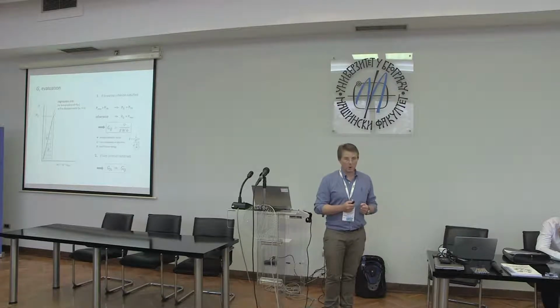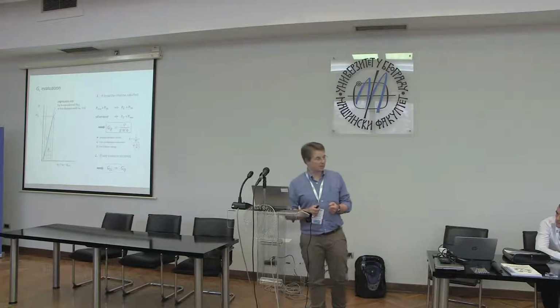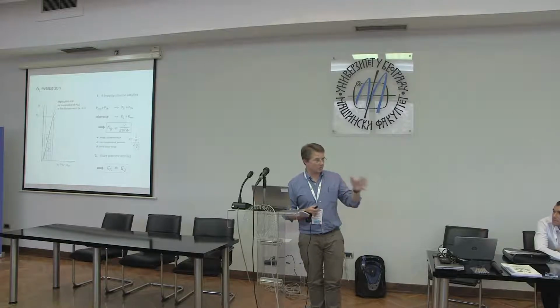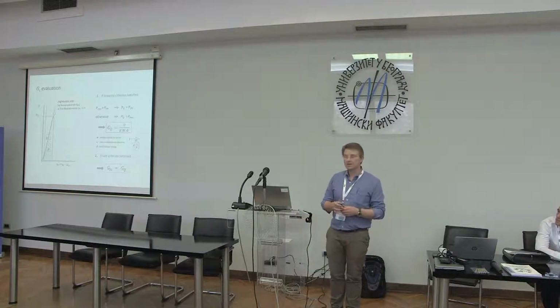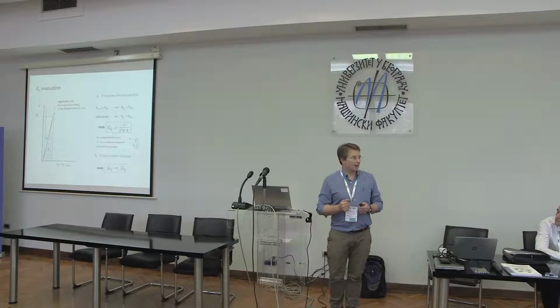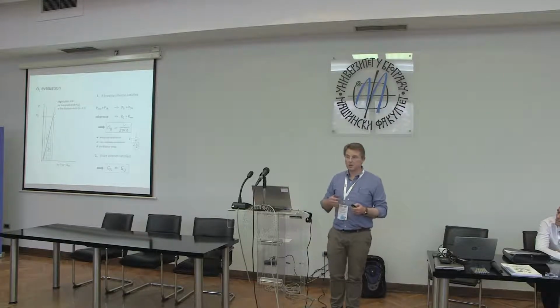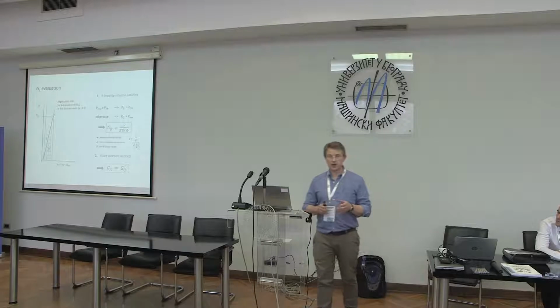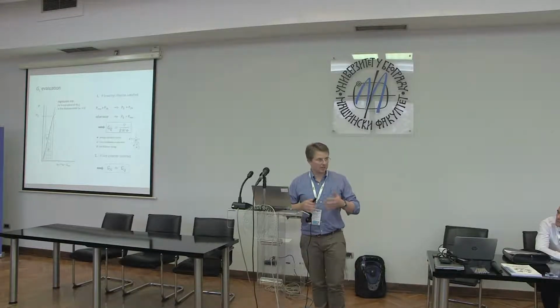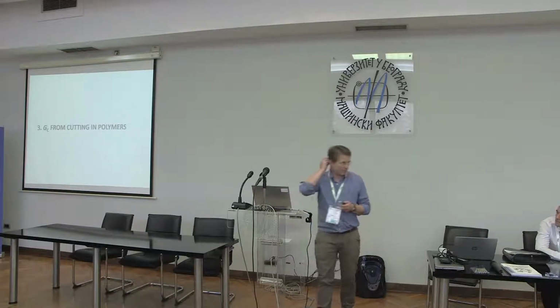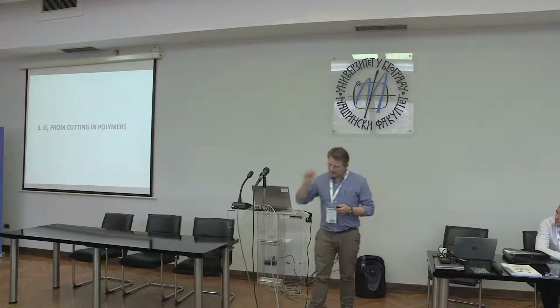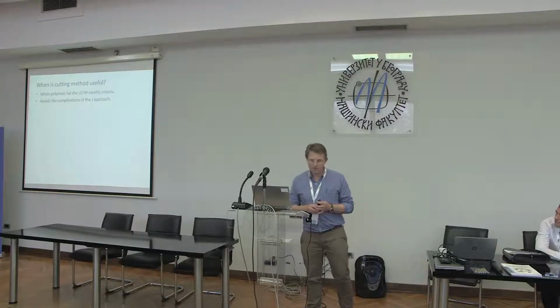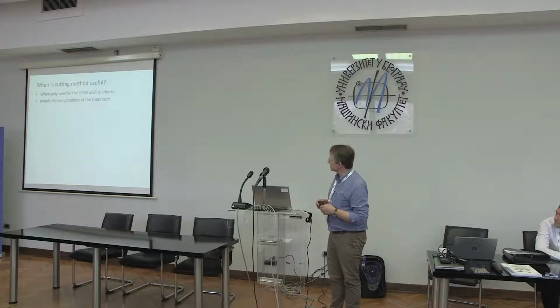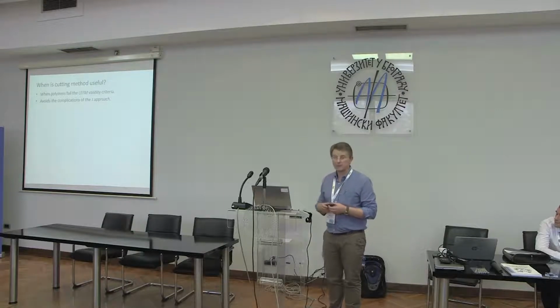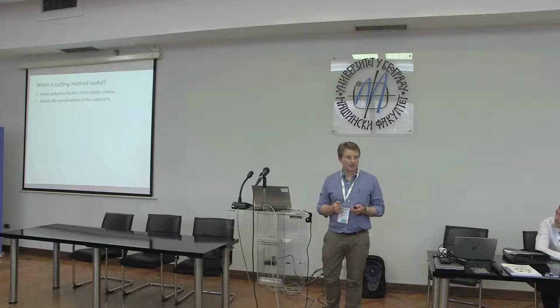It's an important point. Tony Atkins put fracture toughness into metal cutting, and it was an obvious extension then to put fracture toughness, in our case G, into polymer cutting, and to see whether that could be used as a way of extracting G rather than it being an input parameter. This was something that we explored at Imperial College. The basic reason for doing this is that we have many polymers that do fail the LEFM criteria.